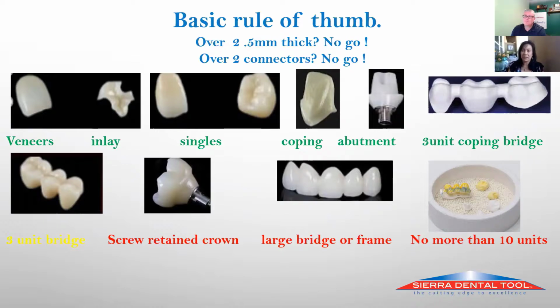The heat rate is going to be much faster, and as we discussed, zirconia is not a very good conductor of heat. So your furnace may reach 1550, but if the units are too thick or there's too much in there, they have not had the time that they need to absorb all of that heat, and they're not going to sinter properly. So that's why it needs to be under 10 units, and the units need to be thin. If you start going into a 3-unit full contour bridge, that's really iffy. You could do it, but you're definitely going to have a less than superior result. It's definitely going to be compromised.